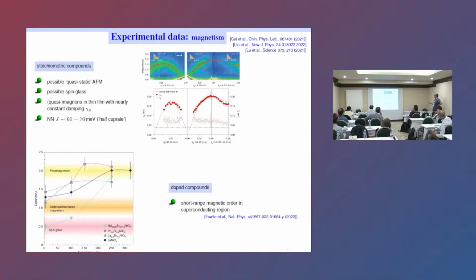I also want to highlight the magnetic features. Again, I stated that the antiferromagnetic order has not been found. There have been indications of quasi-static antiferromagnetic order, spin glass behavior. Then there's been this nice RIXS study, again by Stanford group people and associates, that find paramagnon-like branches in this thin film layer. So there must be some magnetic activity, some local, some antiferromagnetic-like dispersion coming up. Of course, in these RIXS studies I cannot claim any signs of static magnetic order. But still, the dispersion is nice, although the width is quite different. That is much more incoherent than in the cuprates.